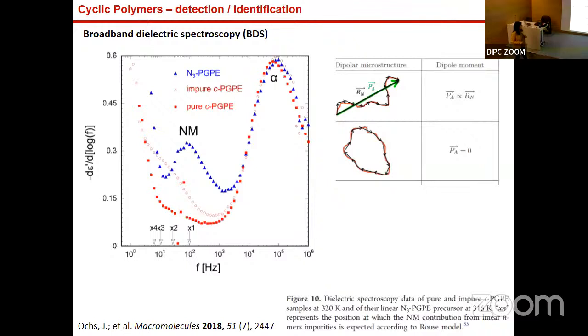Then the dipole moment along the chain contour is proportional to the end-to-end vector. So we get a signal which is proportional to the molecular mass of the polymer. What happens if we cyclize this polymer? The dipole moment is cancelled. So this normal mode relaxation should disappear, and it disappears, in fact, here. This is the alpha relaxation, which is related to the glass transition. We use this as a comparison. All of them have it. And this is an impure sample, where we got some linear impurities. It shows a signal here. But our cyclic polymer has no signal. So in this sense, we could identify that we got the cyclic polymer.